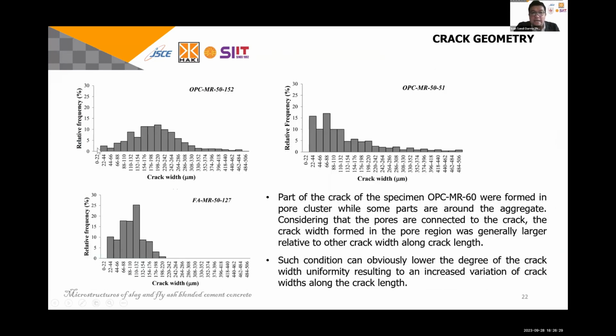And then this is the crack width distribution. We also calculate the crack width distribution using ImageJ. As you can see here, for OPC, the distribution of crack is quite wide compared to the fly ash. It ranges from 0 to 484 for the OPC, while for the fly ash, it is from 0 to only 200.